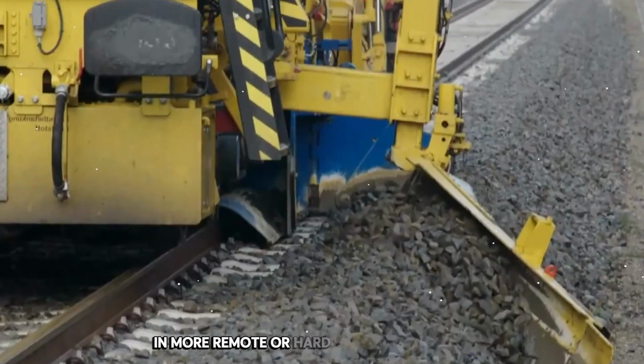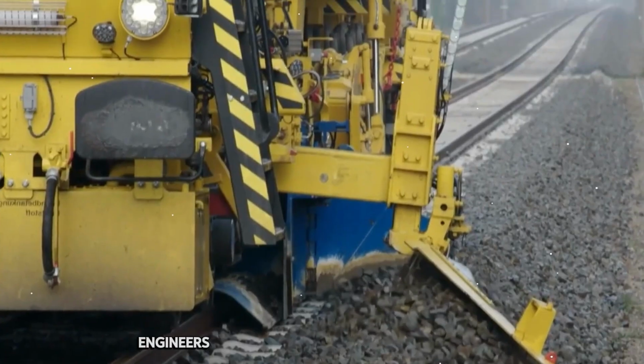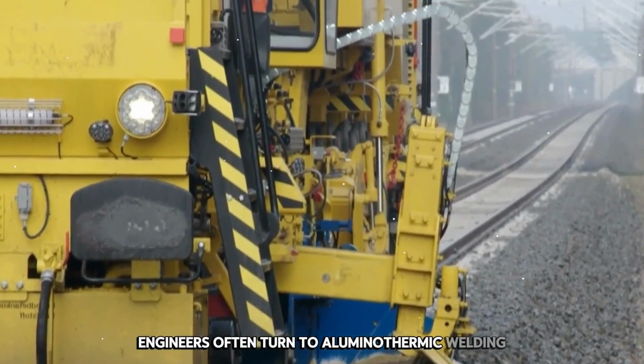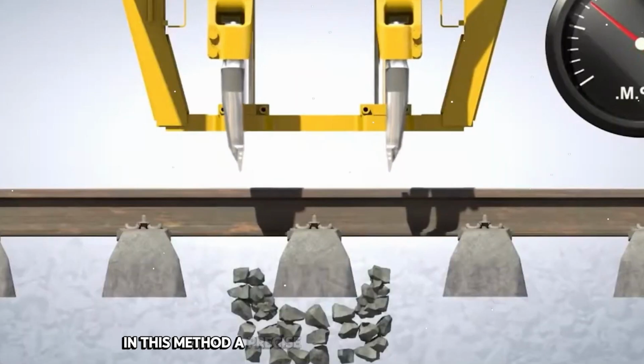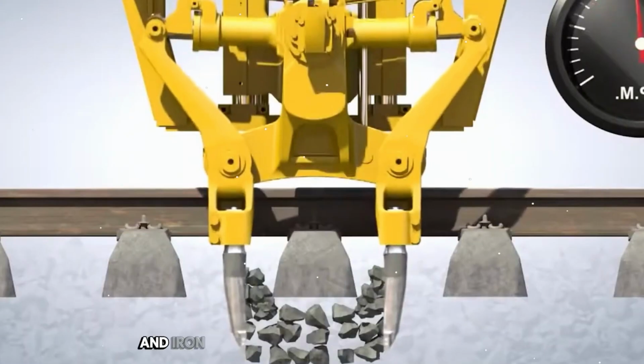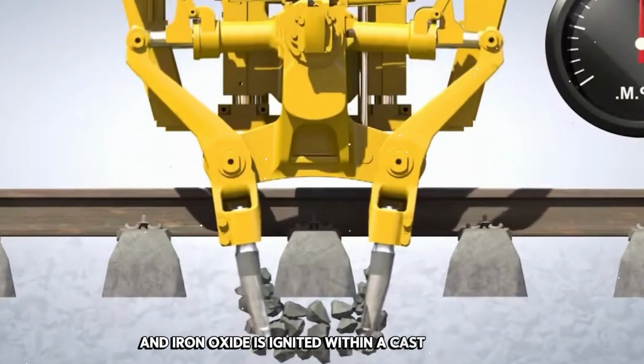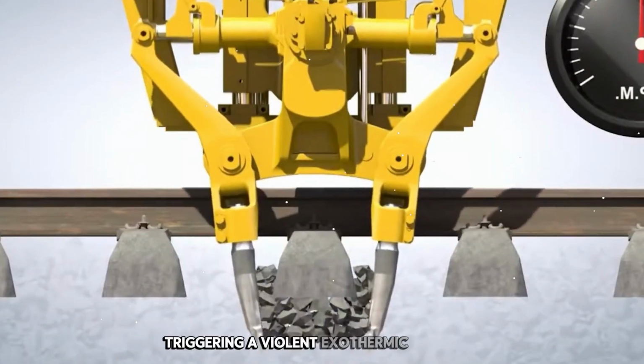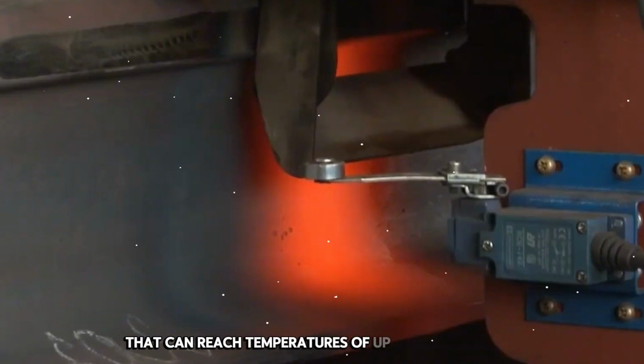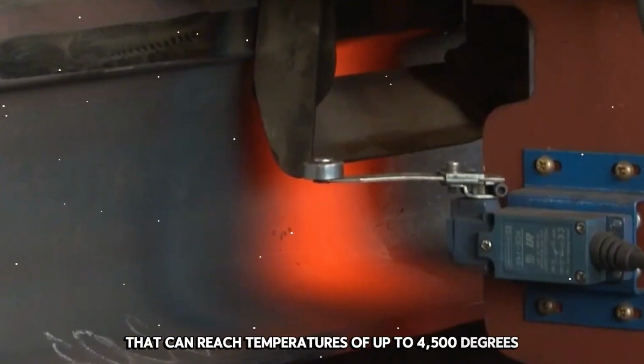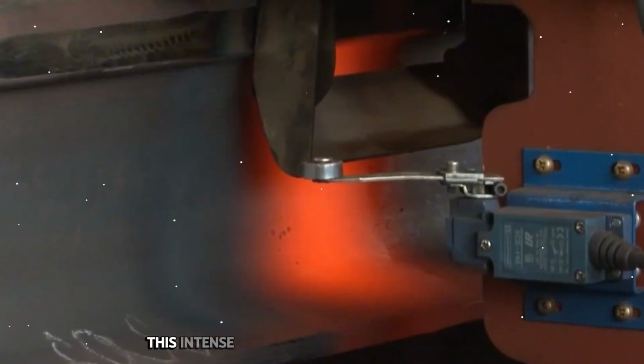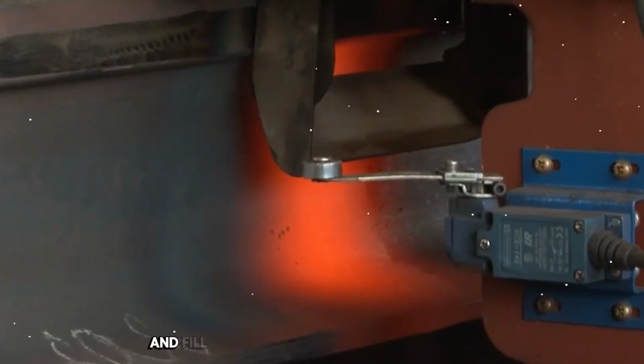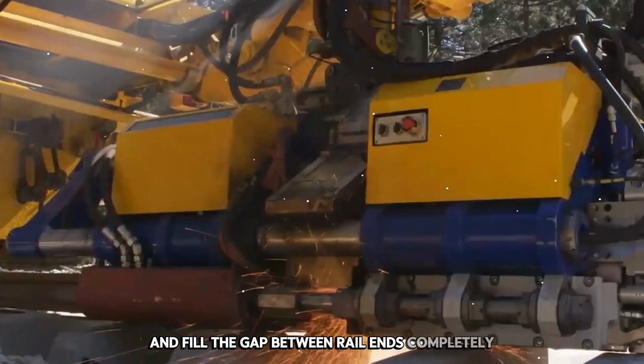In more remote or hard-to-access locations, engineers often turn to aluminothermic welding. In this method, a precise mixture of aluminum powder and iron oxide is ignited within a cast iron mold, triggering a violent exothermic reaction that can reach temperatures of up to 4,500 degrees Fahrenheit. This intense heat is sufficient to melt the steel and fill the gap between rail ends completely.